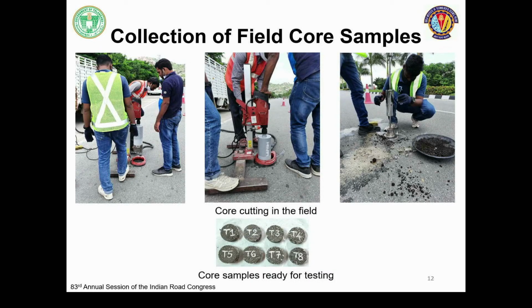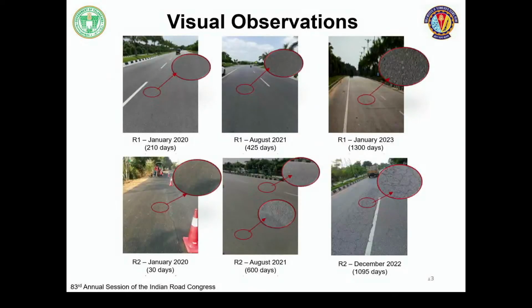What we did was, we have heard of performance studies every 6 months, 4 months once, 3 months once, but we did something different here. From the date of construction, every month we collected the core, tried to find how the density varies or how the air voids reduces and how the bitumen behaves over time to assess the aging in the real field condition. So what are its impacts due to traffic and what are its impacts due to climatic conditions? This is what was assessed in the whole of this study, which took more than 3.5 years.